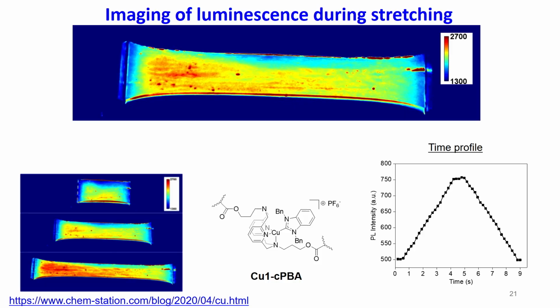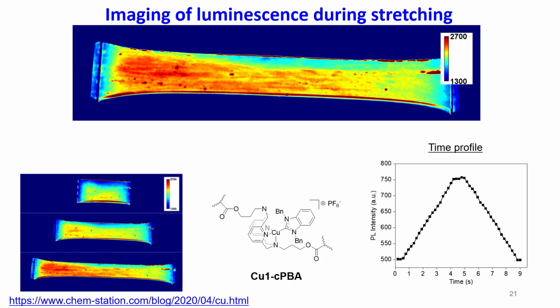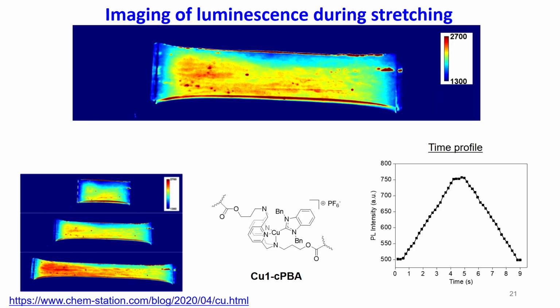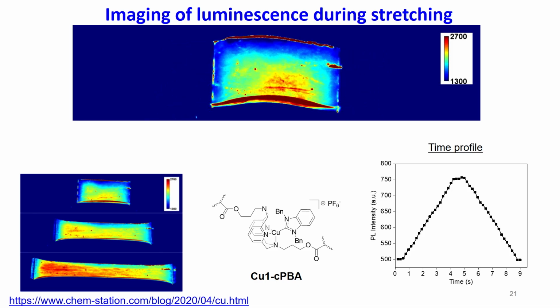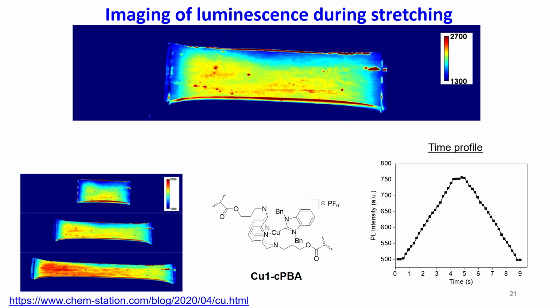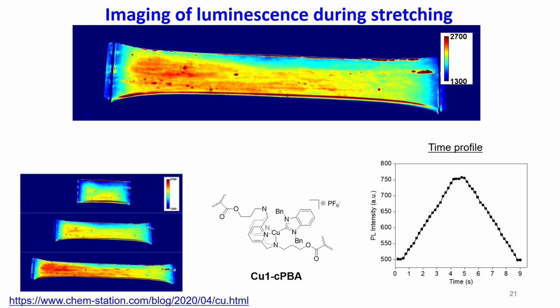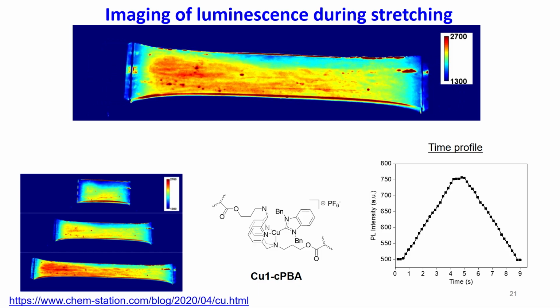So this is actually false color. The colors here are relative colors. They reflect the intensity. So when we stretch the films, the photoluminescence intensity gain increases, and when we release it, it decreases. And this is done on a millisecond time scale.